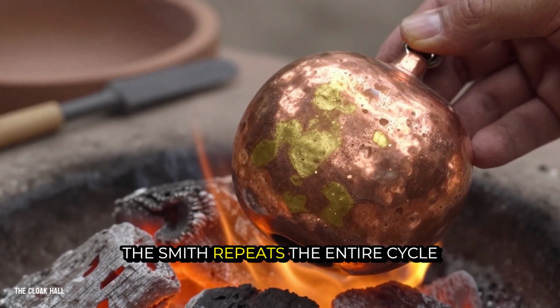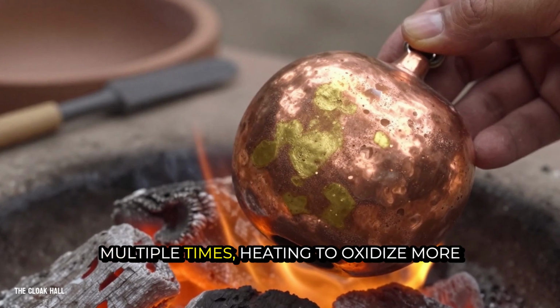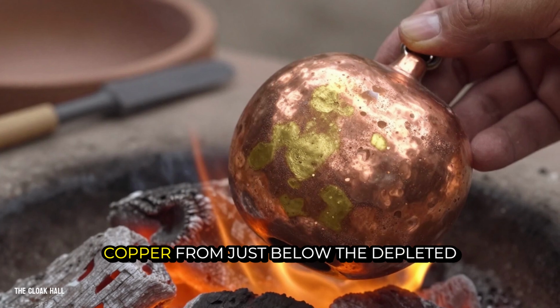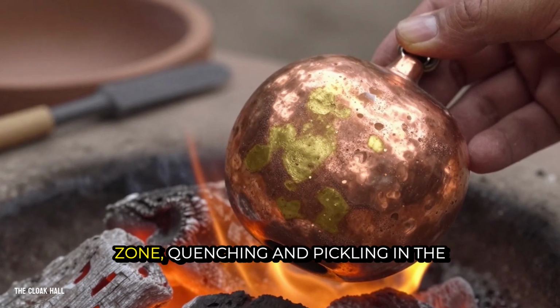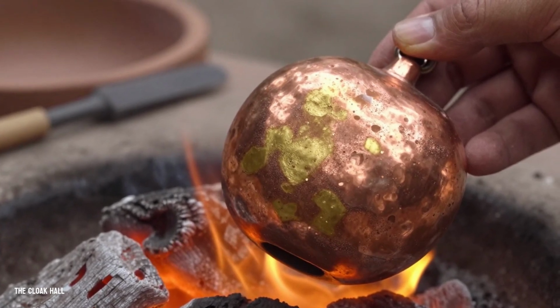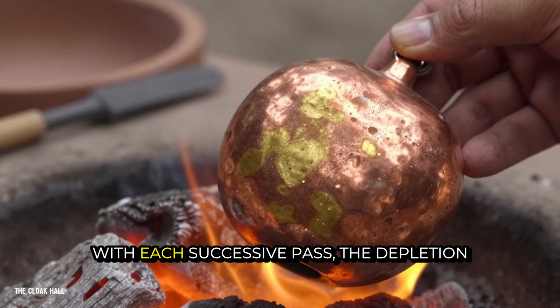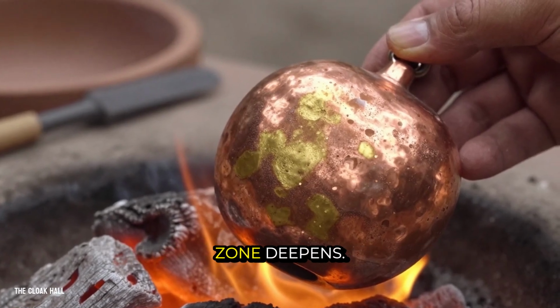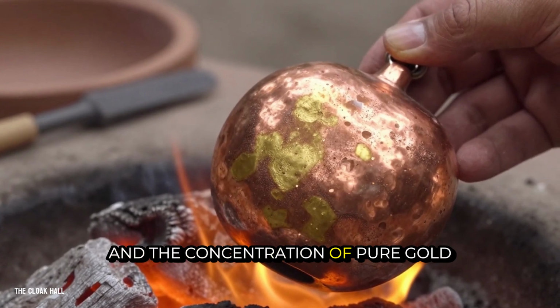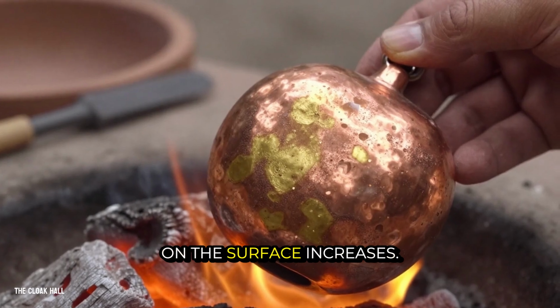The smith repeats the entire cycle multiple times, heating to oxidize more copper from just below the depleted zone, quenching, and pickling in the acid bath. With each successive pass, the depletion zone deepens, and the concentration of pure gold on the surface increases.